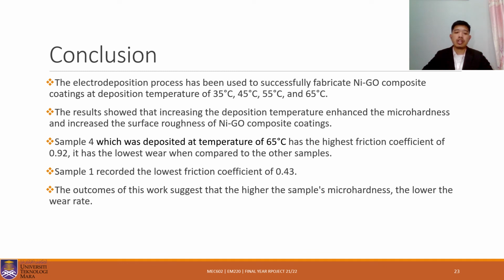For the conclusion, the electrodeposition process has been used to successfully fabricate nickel graphene oxide composite coating at deposition temperatures of 35 degrees Celsius, 45 degrees Celsius, 55 degrees Celsius, and 65 degrees Celsius. The results show the increase in the deposition temperature enhances the micro hardness and increases the surface roughness of nickel graphene oxide composite coating. Sample 4, which was deposited at a temperature of 65 degrees Celsius, has the highest friction coefficient of 0.92. It has the lowest wear when compared to other samples. Sample 1 recorded the lowest friction coefficient of 0.43. The outcome of this work suggested that the higher the sample micro hardness, the lower the wear rate.